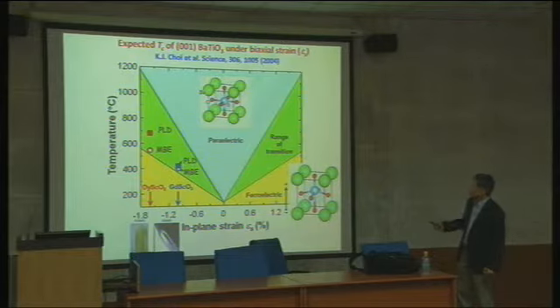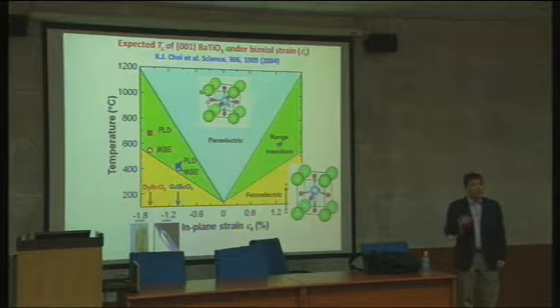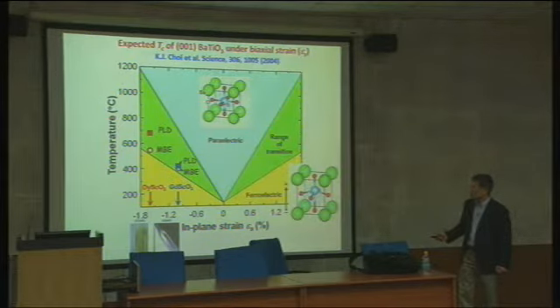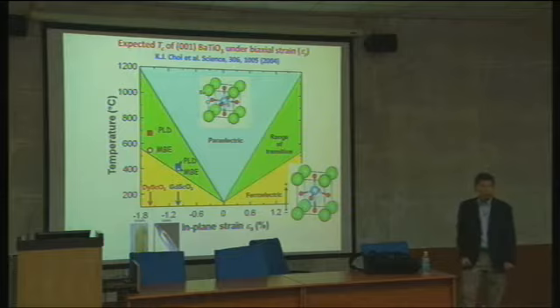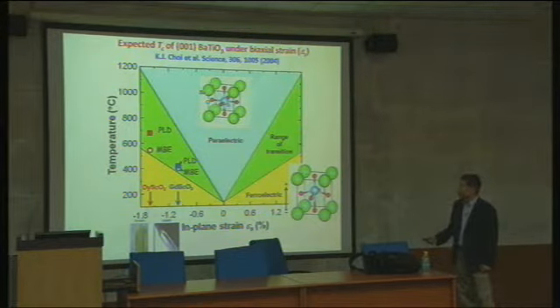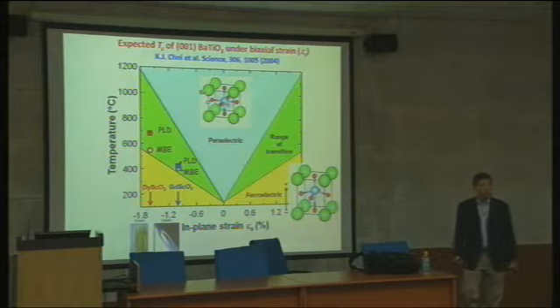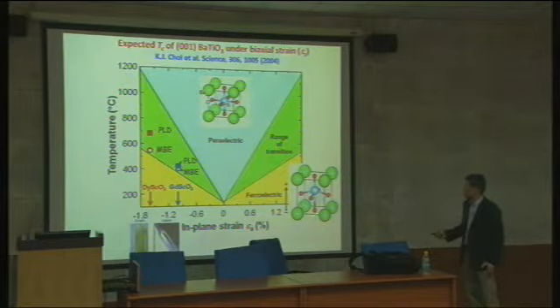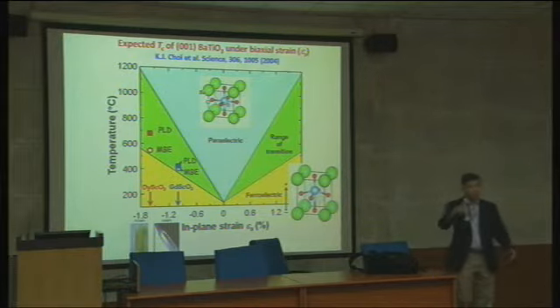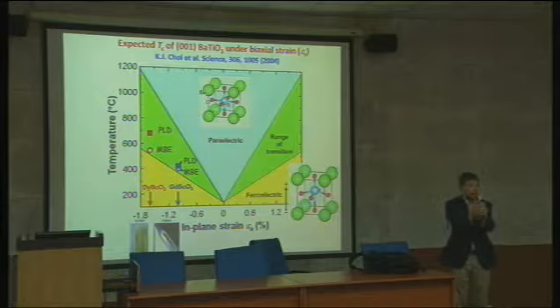And then, for example, this is the phase diagram predicted by phase theory and other calculations. When you compress this by 1 or 2% of strain, your ferroelectric transition temperature increases dramatically. A few hundred degrees Celsius, you can increase it. So can you apply roughly 1%, or 1.7%, or 5%? How can you apply this? You have to find a substrate material whose lattice parameter is smaller than this. You grow this material on it, and this lattice parameter compresses it. It's not uniaxial, it's biaxial. So you press in all in-plane directions.